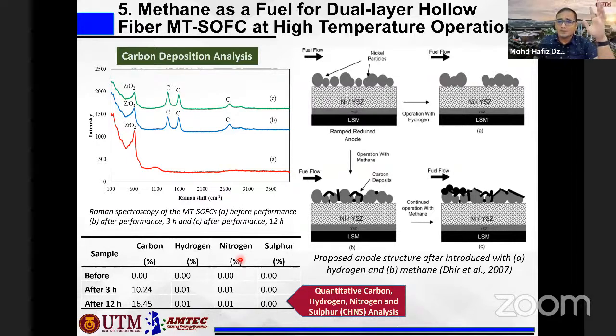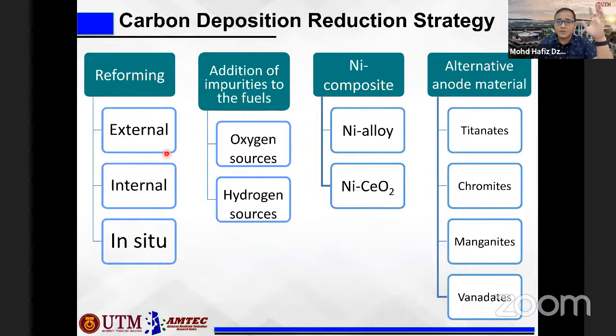So these are some strategies that have been reported in the literature on how to reduce carbon deposition. Either you can use reforming, or you can add some impurities to the fuel. Instead of using 100% hydrogen or 100% methane, for example a hydrocarbon, you can add some oxygen source, but not too much, because if it's too much, it will create an explosion. You can add some more, or you can mix with hydrogen sources as well. Or we can replace or composite the nickel with an alloy or cerium oxide. Or alternatively, we can change the nickel directly to titanates, chromites, manganites, or vanadates, okay, as the alternative anode material. But these types of material are normally more expensive than the nickel type.